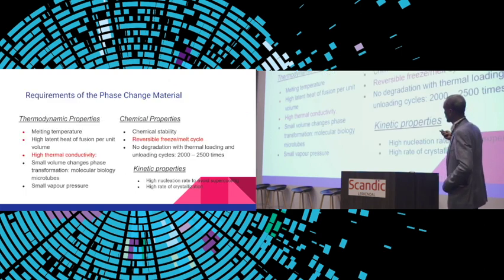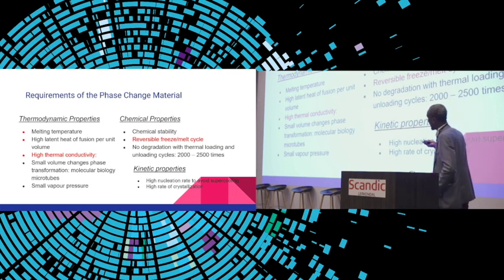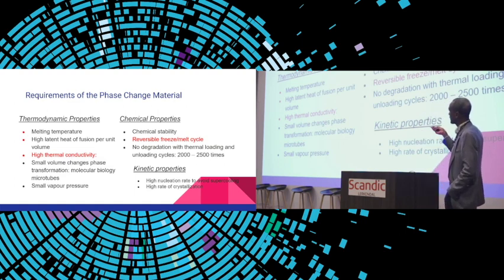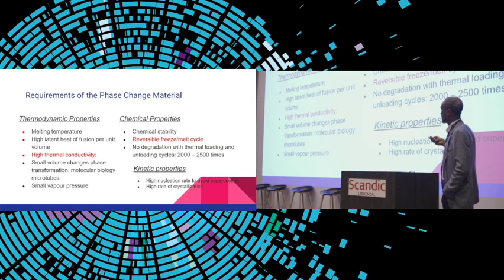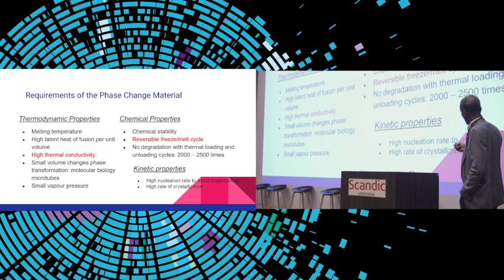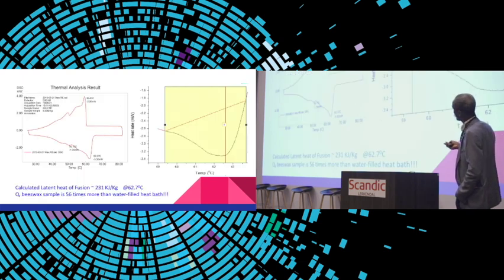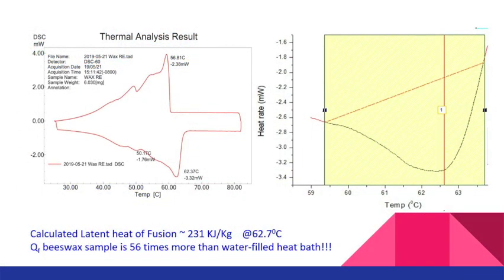And the other requirement, beyond this phase transition point, is that it has to have a high latent heat of fusion, and it should have high thermal conductivity. Unfortunately, beeswax has low thermal conductivity, but I'll talk about how we get over this challenge, and the remaining properties it fulfills very well, as mentioned here. So as you can see from this diagram, this is a differential scanning calorimeter. This deep area is where, at a constant temperature, it absorbs the differential.